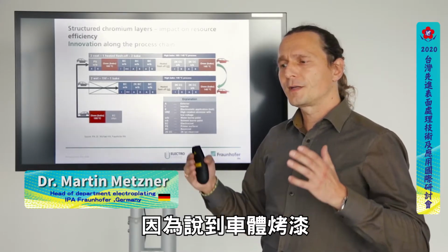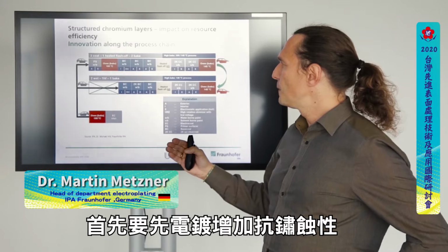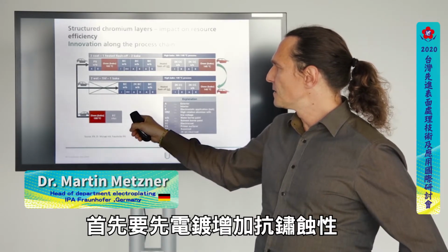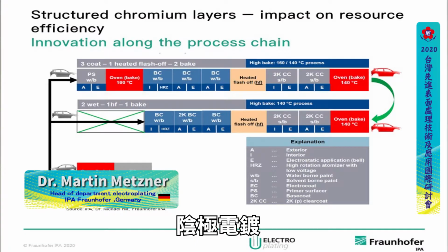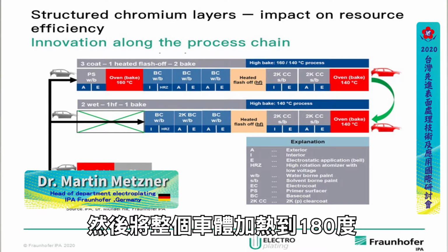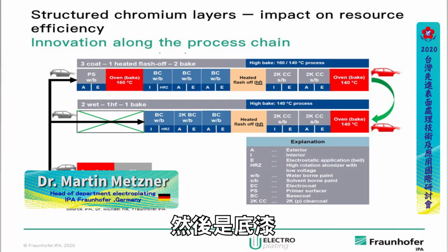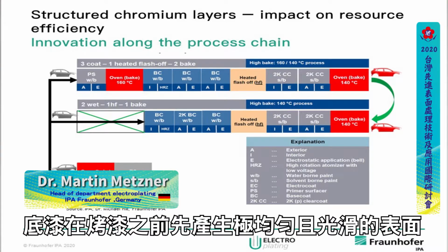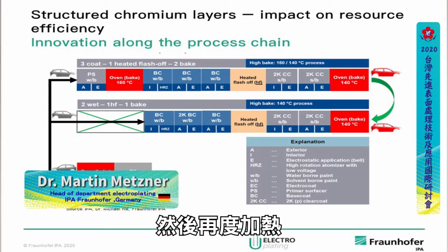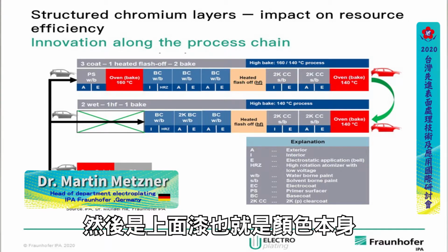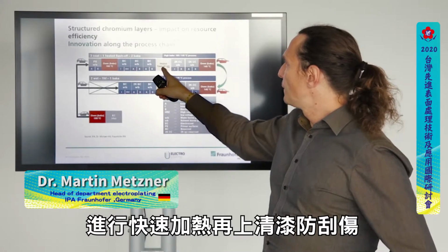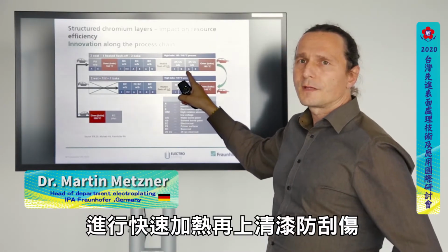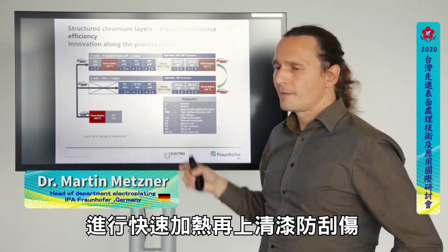Because when you think about painting a car body, in the first step you go for the corrosion resistance in the electrocoating, cathodic electrocoating. Then you heat the whole car body up to 180 degrees. Then you go into the primer. The primer is there to make a very homogeneous and smooth surface before the color painting. You heat it all up again. Then you do the base coat, the color itself, do a flash heating, and then do the clear coat for the scratch resistance and heat the whole thing up again.